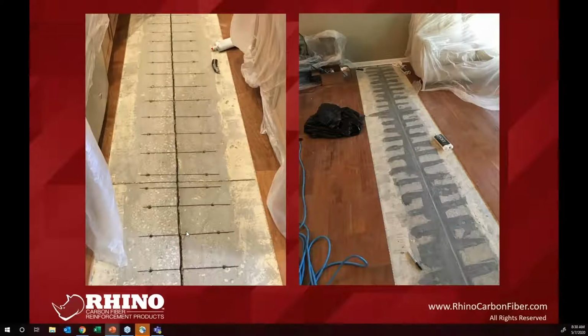This was actually a really cool one. This crack actually involved an addition to a house, and when they went to put it together, they did stitch it together with rebar on the inside, but later on I'll show you a picture on the outside of this addition where the addition was pulling away from the house. The reason it was pulling away was because the outside edge of this walk-in basement flooring, way off to the edge, started to tip, and they had some differential settlement that actually pulled, and this piece actually undoweled itself and slid, so it opened up.